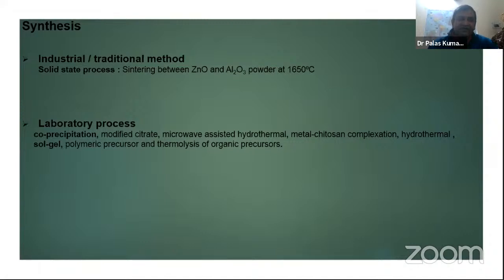Industrially or traditionally, the solid state process is followed, the sintering between zinc oxide and alumina, which occurs at a relatively higher temperature, beyond 1600 degrees centigrade. And in the laboratory, there are so many processes available. Out of them, co-precipitation and sol-gel techniques are the most popular.